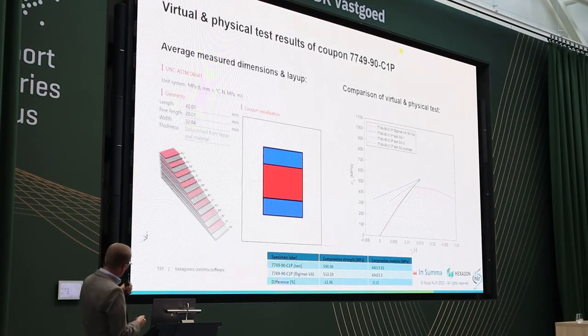You see some of the first results of the coupon cut from a 90 degrees angle from the plates, 16 plies without waviness. First you put in the dimensions of the coupon based on measurements that we did with a digital caliper. So I took into account, as accurately as possible, the dimensions of each coupon.